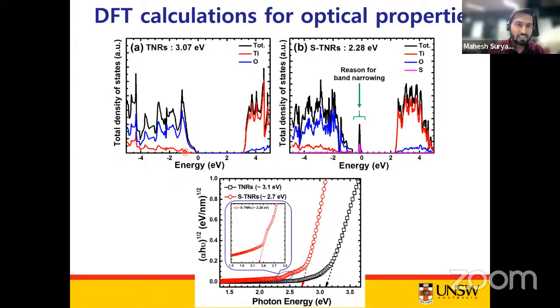As I explained in my previous slide, the reason for the improvement in the PEC performance of these TiO2 nanorods after sulfur doping is that there is a reduction in the band gap, or simply we can say there is an upshift of the valence band edge because of the sulfur doping.